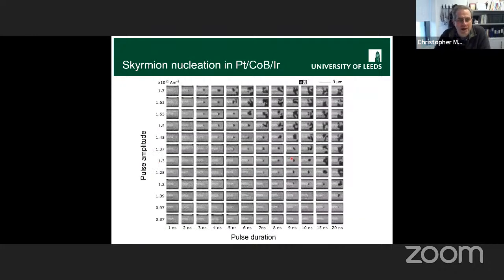So basically, this is what we see. Here we've got lots of little micrographs with the finger always coming in from the left-hand side. This is how long the current pulse was that we injected, and this is the current density, which we've calculated once it's spread out into the wire. Down here, the pulse is either too short or too weak, and nothing happens. Up here, the pulse is either too long or too strong, and we've overheated our wire and filled it with some sort of complicated domain pattern. But there's this band across the middle where we get a single patch of dark contrast, a single skyrmion appearing at the tip of the finger.